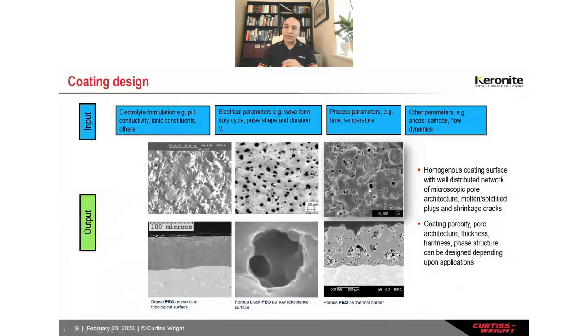On the right-hand side, you can also create an aluminum oxide or magnesium oxide spinel type coating, for example, where you can also trap porosities with air trapped, to give properties with very, very low thermal conductivity and low specific heat capacity, for example, for applications like thermal barrier coating or piston applications.